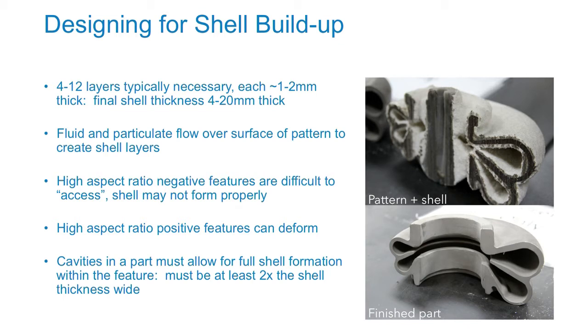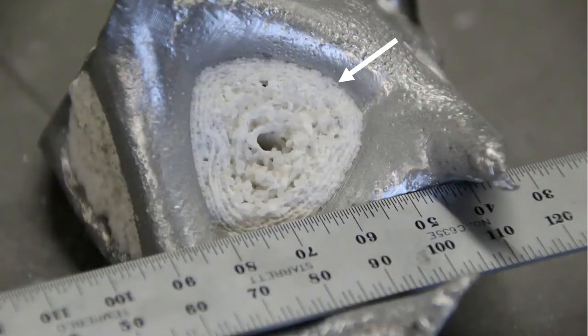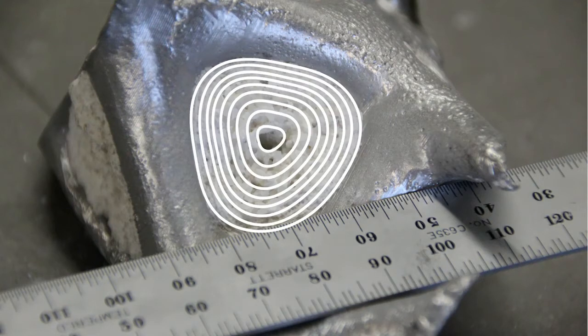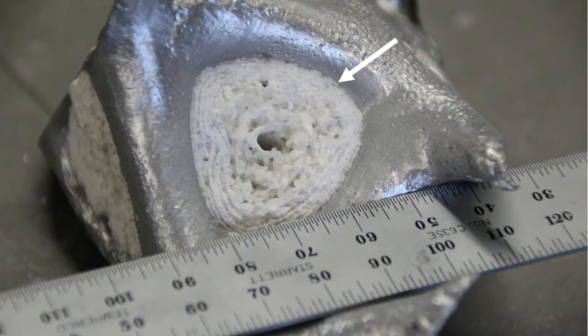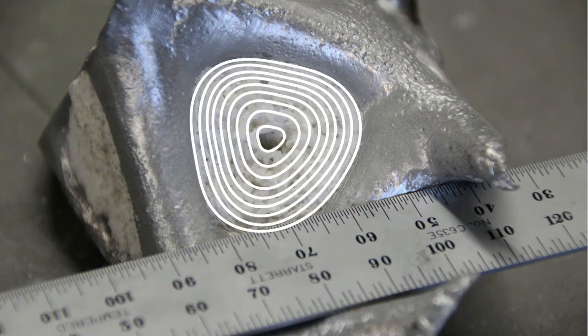Probably one of the most interesting and important things we learned exploring these lattice geometries is around negative features, so cavities in your geometry. As a shell is built up, this is just a part of a three-dimensional lattice geometry here. You can actually see the 9 individual layers of that shell, of the ceramic slurry, and then the back coat of stucco here. And what's important is to make sure that all of those negative features are at least twice your shell thickness, so that you can build up a complete shell. Because otherwise you're going to essentially end up with a defect in your mold.